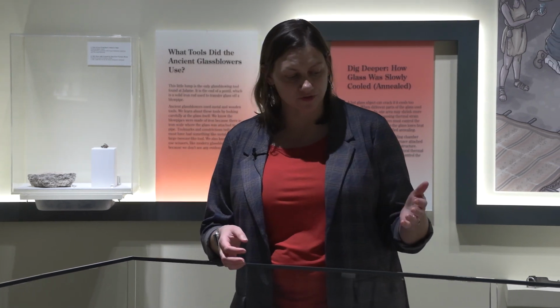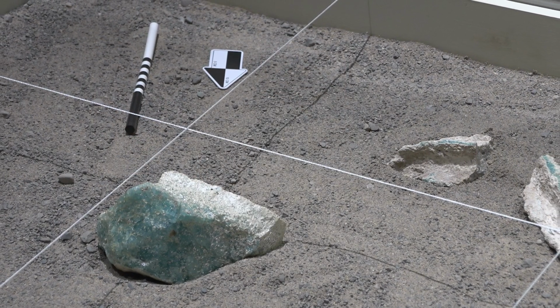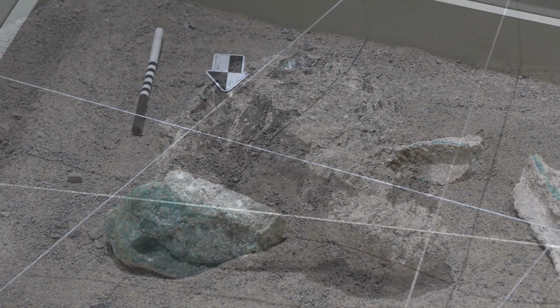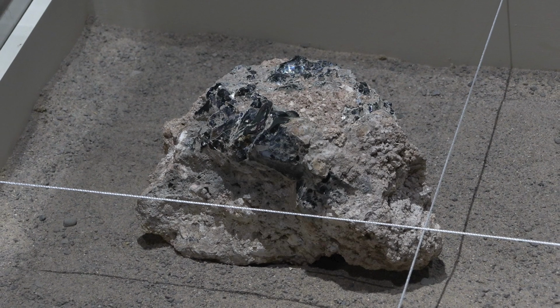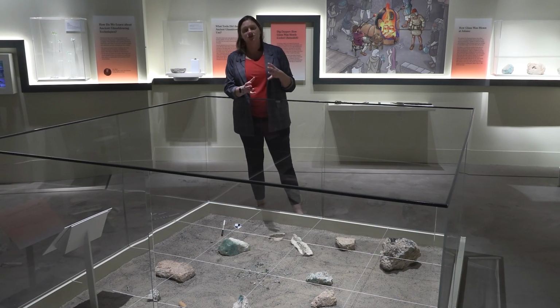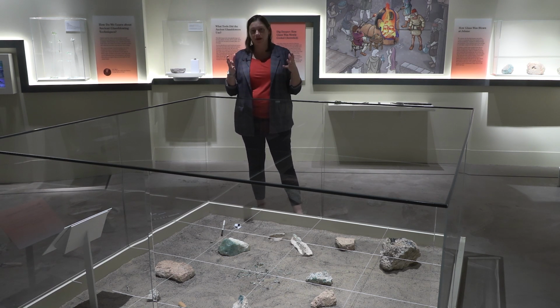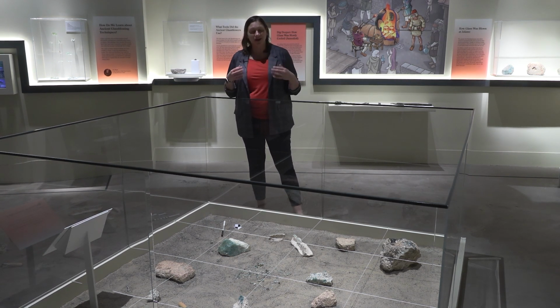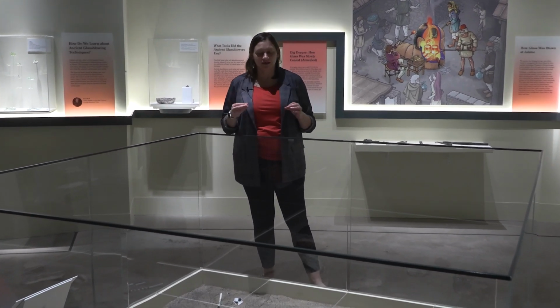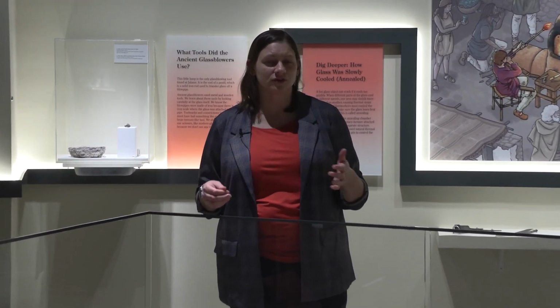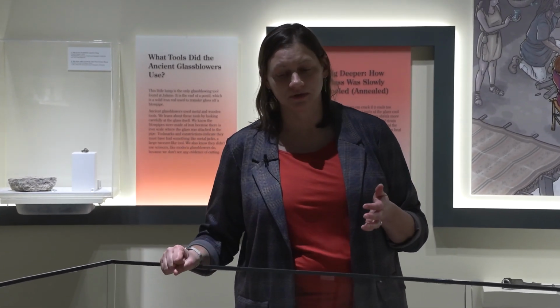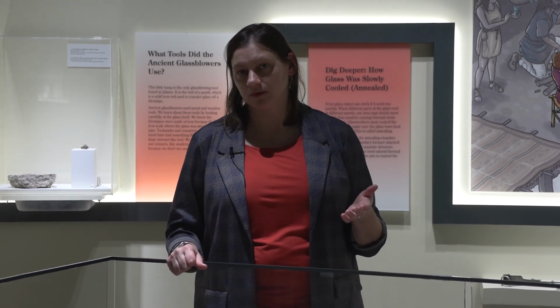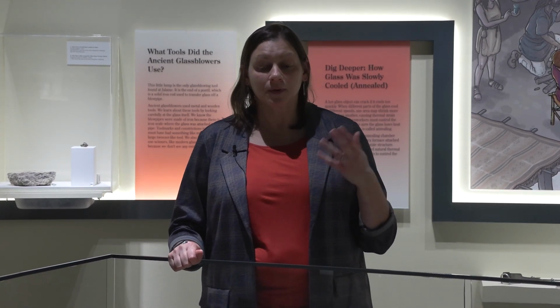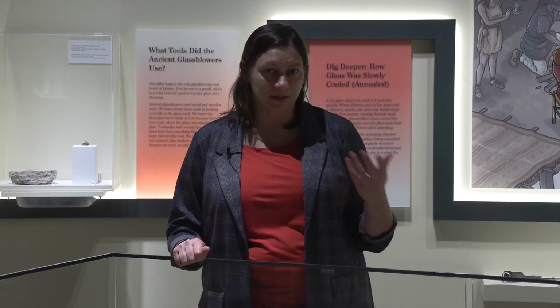So he was immediately able to point out things like these large chunks here that look kind of like glass and kind of like not glass. And what those are is that they're actually part of the wall of the furnace where the glass has eaten into the side of whatever is trying to contain it. Hot glass is incredibly corrosive, and glass furnaces, even today, usually don't last more than 5 to 10 years or so. And that's about how long we think that the Jalame workshop operated, in part because the furnace might have failed,